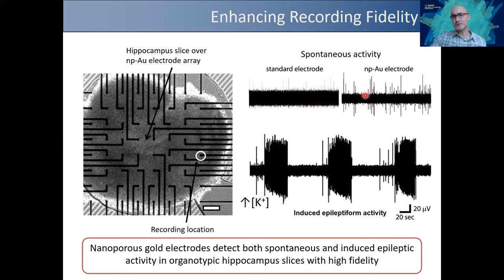When you go to the nanoporous gold electrode, you can reduce that background noise, and this reduction is mainly due to the reduction in the electrode impedance. So remember those two resistances that I've talked about. But you also see high signal strength on the nanoporous gold electrode, which cannot be explained by the reduced electrode impedance.